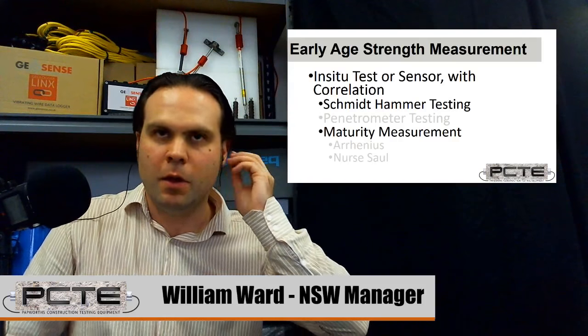So I'll mention as a way to improve cylinder breaks is to use match temperature curing. Now, in situ measurements, we're using it for the same reasons, but now we are forming a correlation to a test mix done in the lab. And Schmidt hammers everyone should be relatively familiar with. There is an ability to use those for early age strength under the right conditions. And maturity measurement is a very powerful tool for on-site or precast applications where you want to use that to supplement or replace early age cylinder breaks. It captures the real strength at the point of the sensor.